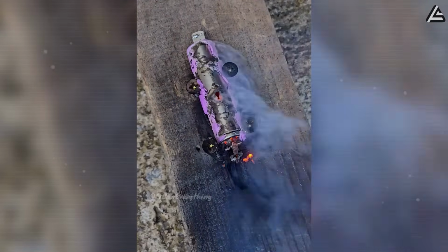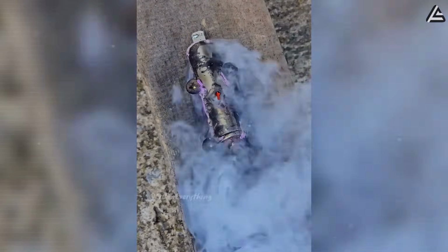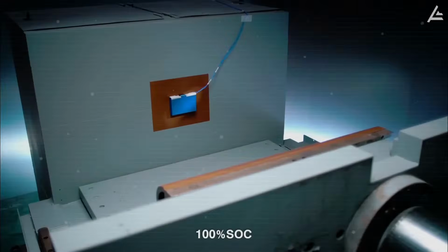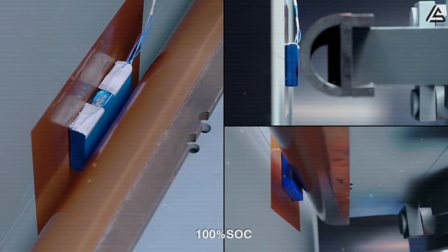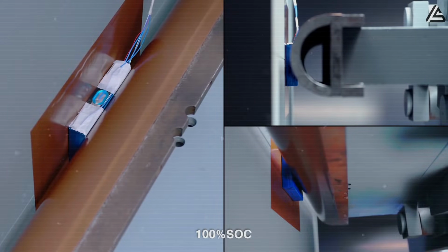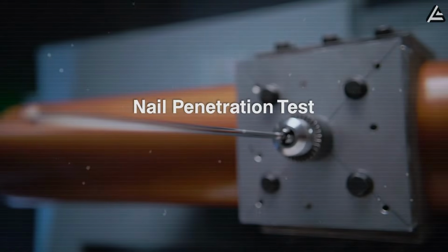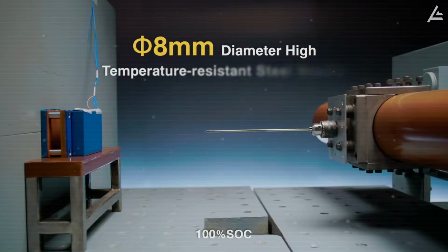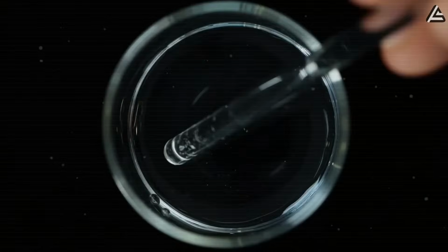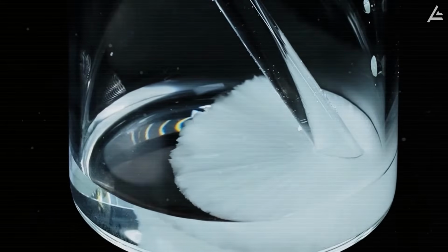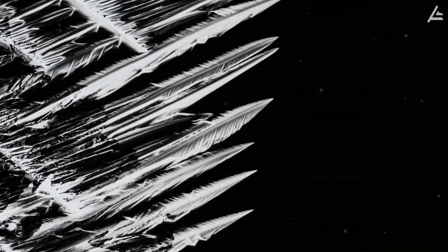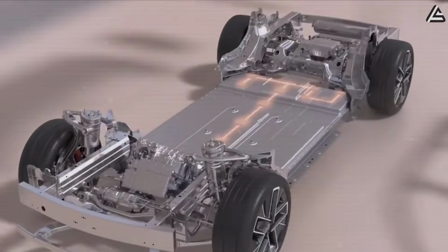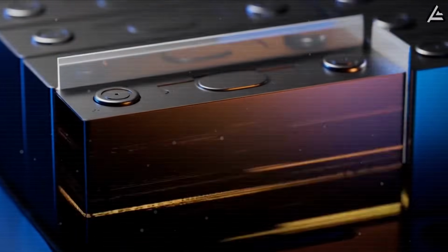With a lithium battery, friction and impact forces can spike cell temps to 90 to 100 degrees Celsius. Once separators rupture, flammable electrolyte leaks out, metal sparks fly, and the worst-case scenario begins. With aluminum, cells rise only to about 70 to 80 degrees Celsius in the safe zone. And even if they break open, there's no liquid fuel to catch fire, no chain reaction spreading flames. In the same situation where dendrites inside lithium would trigger shorts and explosions, aluminum cells simply stay put, warm a little, and keep everything under control.